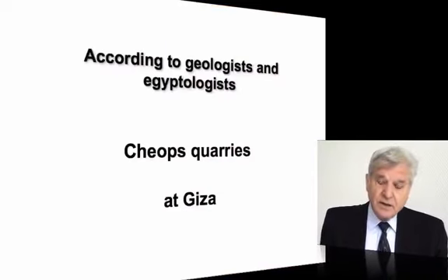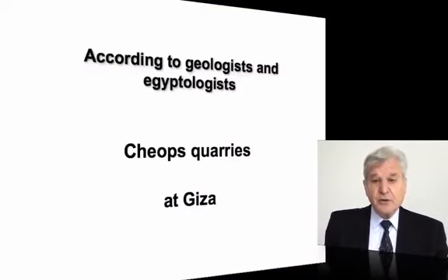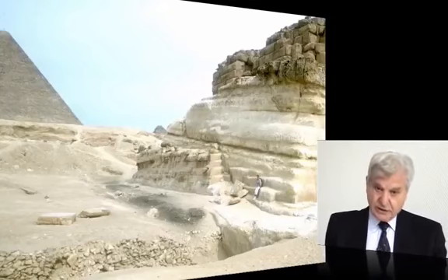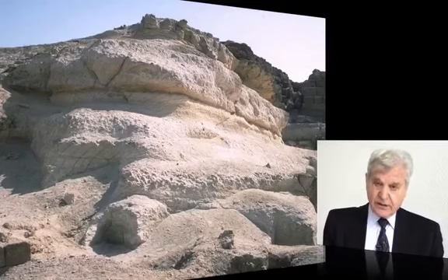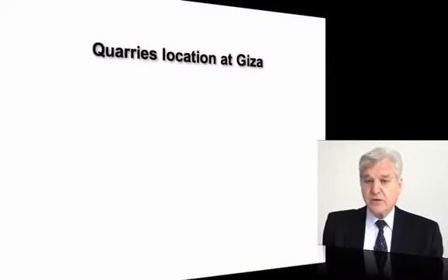Egyptologists and geologists agree with the locations of the quarries where the stony material is coming from. We have located the Cheops quarries at Giza, and this is where they are. If we look at the layers, we see that the material was extracted in a very weak limestone that is absolutely not dedicated to the purpose of making building blocks, but it is this layer of soft limestone that was used to build the pyramid of Cheops. And we see there are other quarries that have been used for the pyramids of Khafre and Menkaure. So we know the location of the quarries at Giza.